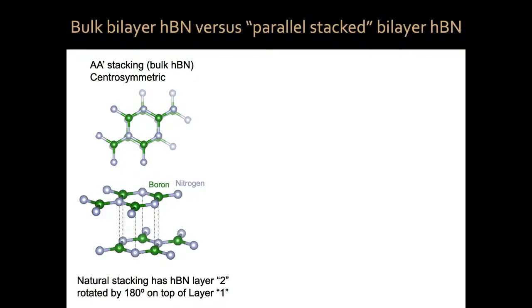Okay? So that's sort of the magic of the type of things that we can do with this non-equilibrium assembly of 2D materials. So the material I'm going to talk about is hexagonal boron nitride. I've already mentioned this material as a nice dielectric for graphene devices. Now we're actually going to make use of it. So bulk hexagonal boron nitride also has a honeycomb structure, where now the A and B sublattices of graphene are actually different atoms, boron and nitrogen, okay?